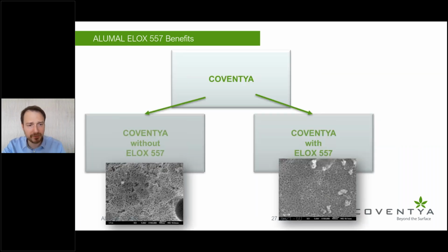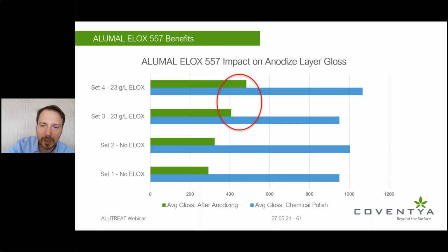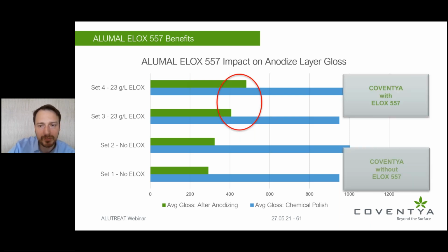But more importantly, we have briefly mentioned that the distribution of the pores is very important for the homogeneity of the color, but it is also very important for how transparent your anodic oxide will be. Because if those pores are not orderly distributed, the oxide layer will not only be less transparent, it will be opaque. Therefore, the color that you're going to get, or perceive, will be much duller, and it will be different.